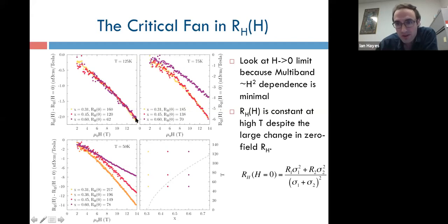If you go to lower temperatures, there's still a region in which curves lie on top of each other, but the most overdoped samples start to show a weaker field dependence. And if you go to lower temperatures still, that trend continues, with the intermediate dopings showing a slightly weaker field dependence, and the common field dependence existing only over doping near optimum. So once you just plot the field-dependent part of the Hall coefficient, it becomes relatively easy to see that there is a constant thing whose constancy is shrinking as you decrease temperature.